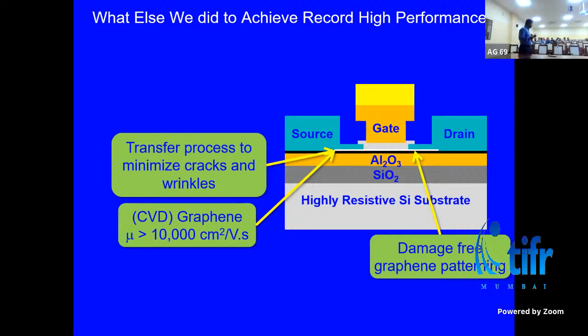For example, if you have water trapped under graphene and you try to do some high temperature process afterwards, it becomes steam. It tries to break graphene and evaporate it, which means it will damage graphene, and you will not be able to see that water by bare eye or microscope. So you have to deal with all of this, right? Optimize that process, and still get high mobility graphene.